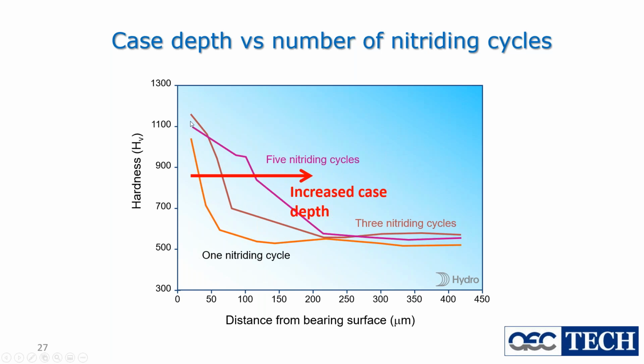So after 5 nitriding cycles, provided we've done everything else right, we have a much, much deeper case depth that looks a whole lot more like that sketch that I showed you at the beginning, which is our ideal case depth. We don't want to try and do this in one go, because as Yaya is going to demonstrate to you, if we try to get too aggressive in pushing that nitrogen in, we produce the wrong phase. And I'm sure some of you have seen dies which have gone crazed or brittle because of it.